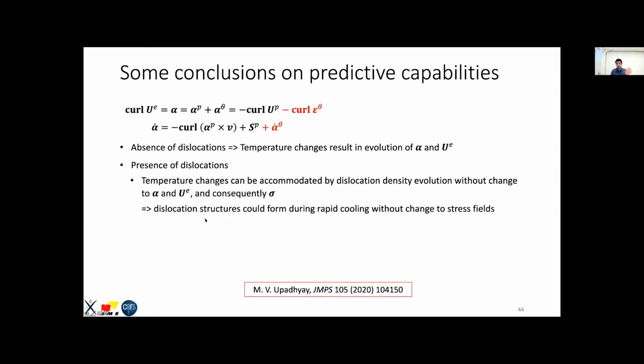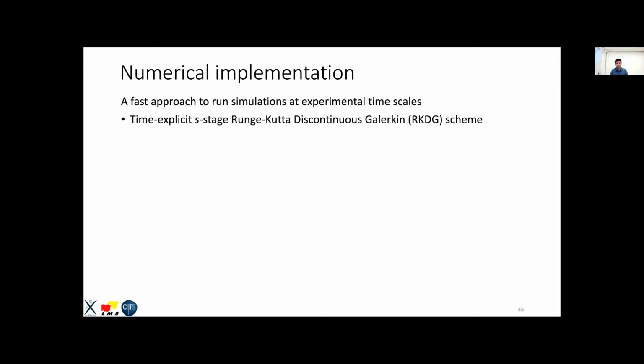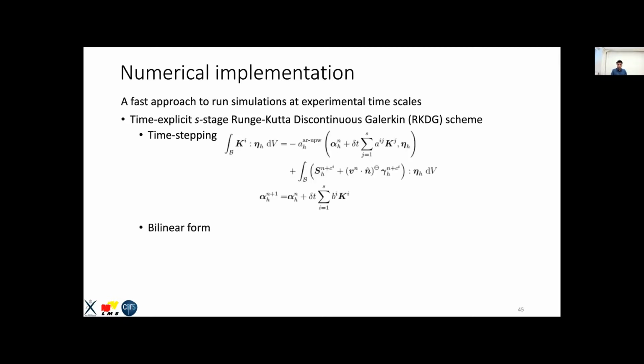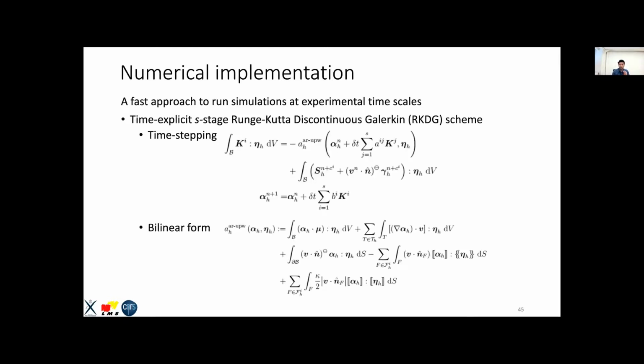So now you can have dislocation structures that could form during rapid cooling without changing the stress field at all. This is allowed. It doesn't mean that it happens all the time. And this equation shows that dislocation dynamics results in local temperature changes. Okay, so I did a numerical implementation of this with the Runge-Kutta discontinuous Galerkin scheme.